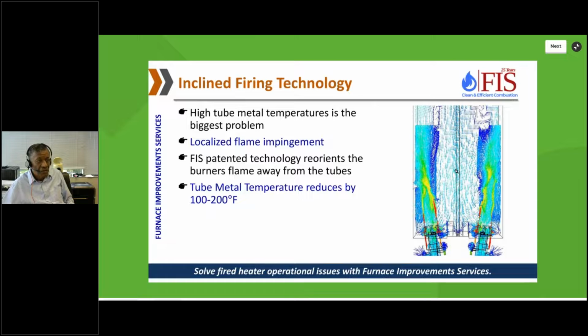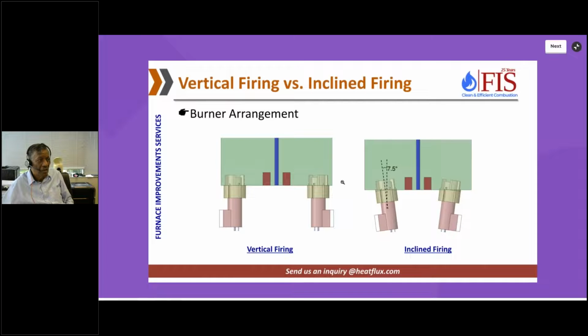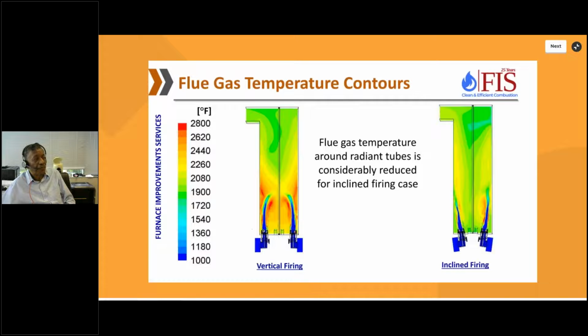There are 2 rows of burners with a tube in the center. So this is a typical configuration of a conventional vertical firing, upfront firing. And here what we have done is put the burners at an angle of about 7 degrees, and we are trying to fire it across the wall, around the wall. I just want to show you a few of these things. You can see the difference: the flue gas temperature contours are closing towards the tube, whereas when I do the inclined firing, those red zones kind of disappear.